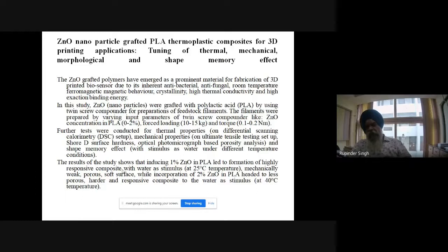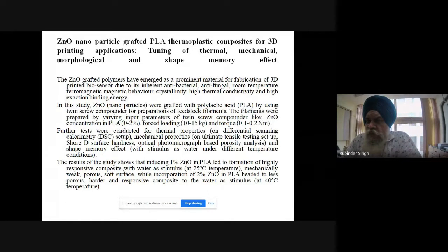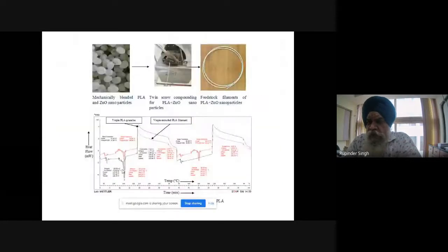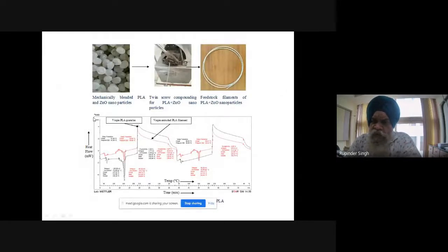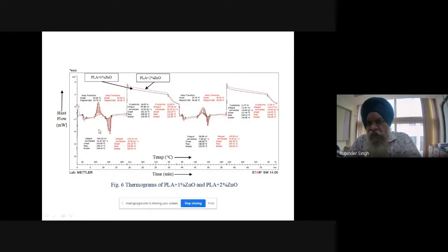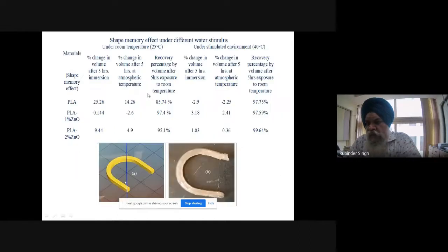There is another example, typically for the sensors. So ZnO nanoparticles were reinforced into the PLA, and we are interested in their thermal, mechanical, morphological, and shape memory effect. Now this will be more clear from this picture. So I have ZnO nanoparticles that were put into an extruder. So some feedstock filament was prepared. That feedstock filament was put into a printer for printing some of the components. This is the picture for the thermal stability value. Then once I add ZnO in different proportions, 1%, 2%, I can tune this material for better thermal stability.